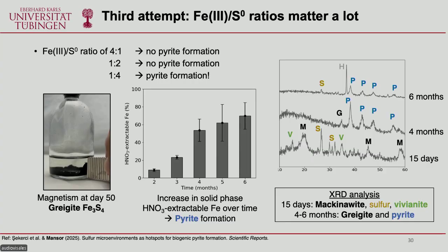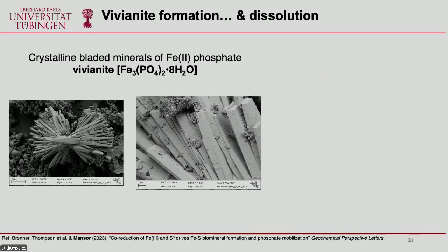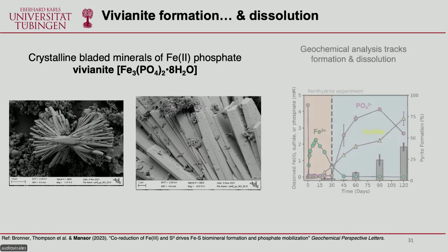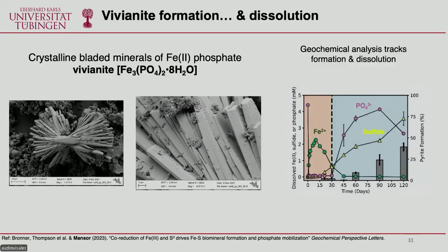And then we confirm this with X-ray diffraction. Within the first 15 days, we have mackinawite and vivianite, an iron phosphate. And then within 4 to 6 months, we have greigite and pyrite, and only pyrite at the end. So great, then we can form pyrite. Let's take a look at vivianite for a short while, because it has these crystalline bladed minerals, which are very typical of this crystal. And we can track its formation and dissolution by using geochemical analysis.